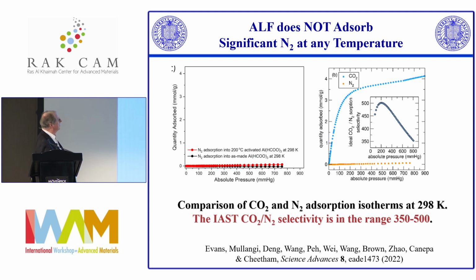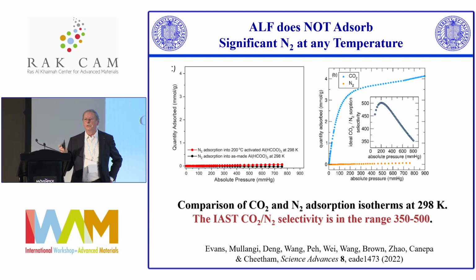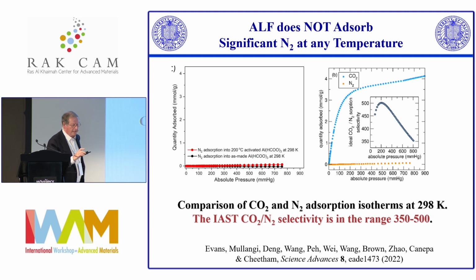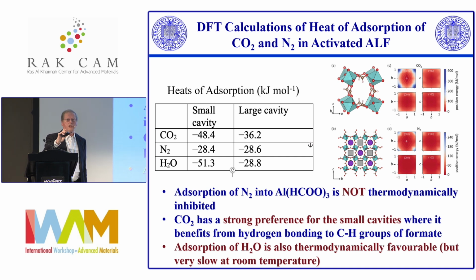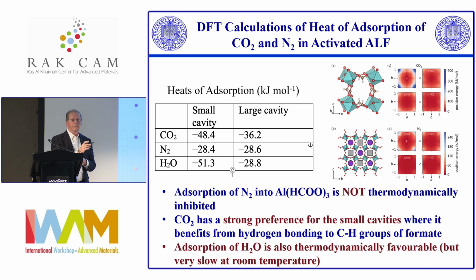So when you calculate the IAST selectivity from the separate isotherms, you get a selectivity for CO2 over nitrogen in the vicinity of 350 to about 500. So it has a massive selectivity for CO2 over nitrogen. And of course, we started to think about whether we could use it for flue gas applications, for example, which Mohammed talked about the other day, which is a very challenging application. Piero and Jerry in Singapore did a lot of calculations on this and other sorbates.